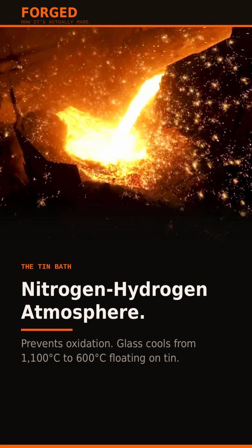The float bath is a long, enclosed chamber filled with molten tin, maintained in a nitrogen-hydrogen atmosphere to prevent the tin from oxidizing. Molten glass is poured onto the tin at about 1100 degrees and floats across it, spreading out naturally under gravity and surface tension to a uniform thickness. As it moves through the bath, it cools slowly. By the time it exits onto rollers at about 600 degrees, it is a continuous ribbon of perfectly flat glass, optically smooth on both surfaces, the top polished by surface tension, the bottom by the tin. The float process is so effective that virtually all flat glass in the world is still made this way.